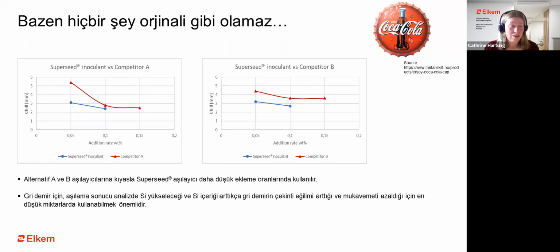So it also shows that, I would say, some inoculants are just better and provide more consistent performance regardless of addition rate. That's what you want from an inoculant as well, and what the high potent inoculant is providing: a better performance at the lower addition, and a consistent performance at varying addition. So this hopefully shows the strength of superseed, and superseed is also a product that is developed for inoculation of high strength gray iron.